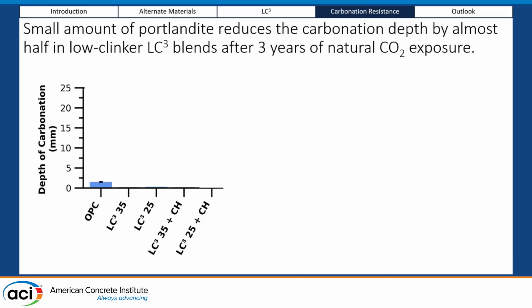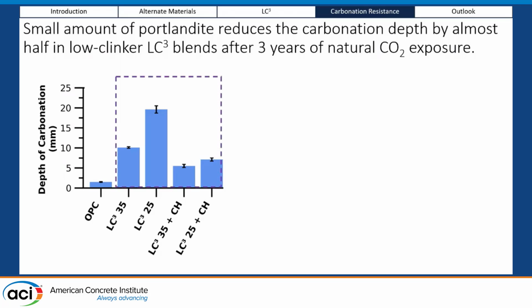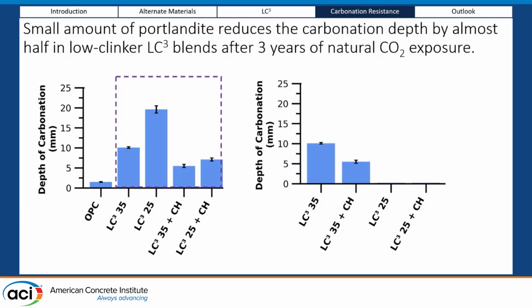OPC fares really well in natural carbonation because of its enhanced buffer capacity and high amounts of reactive lime. LC3-35 and LC3-25 show very high depths of carbonation compared to OPC because of their reduced clinker contents. With a certain amount of portlandite added, we reduce the depth in these graphs. Now, to focus on these LC3 blends, we have to understand how much it has reduced. For the LC3-35 with portlandite, we have about 45% reduction in the depth of carbonation. Similarly, for the LC3-25, we have an even greater reduction in the depth, about 64%.